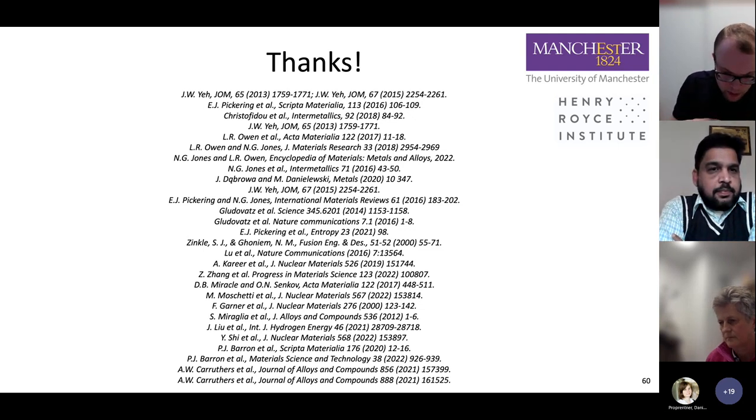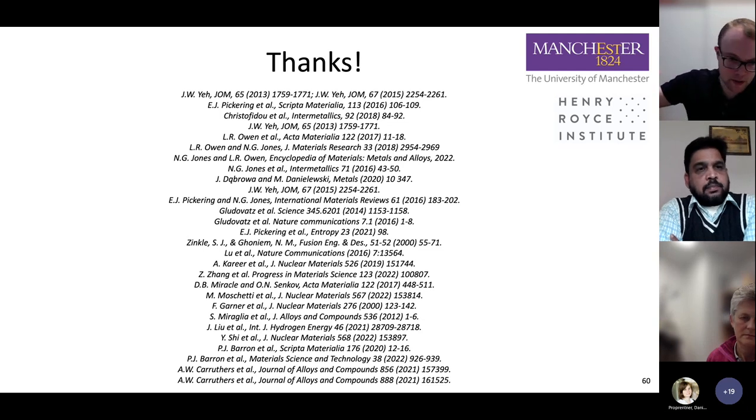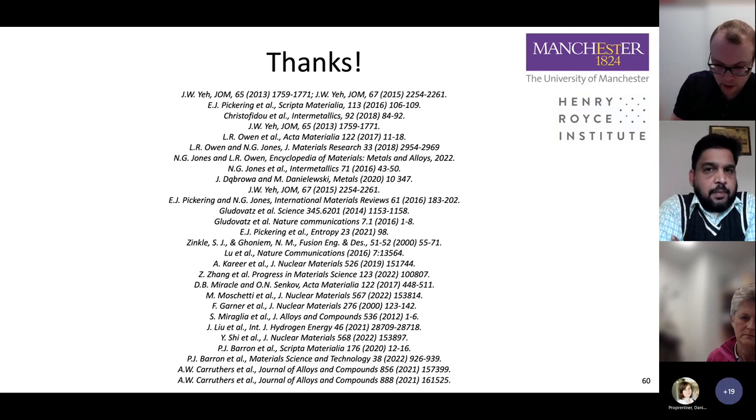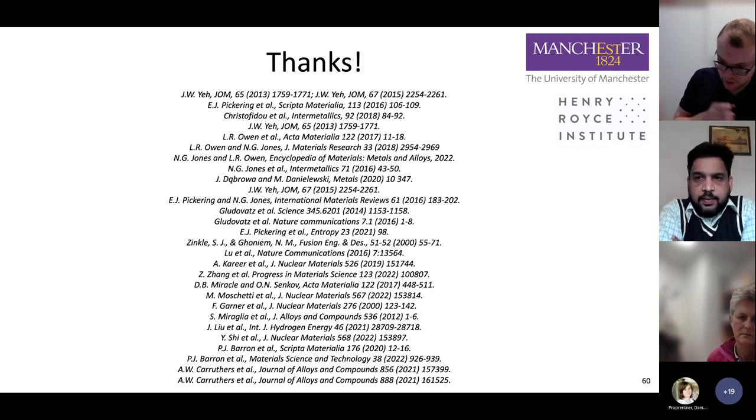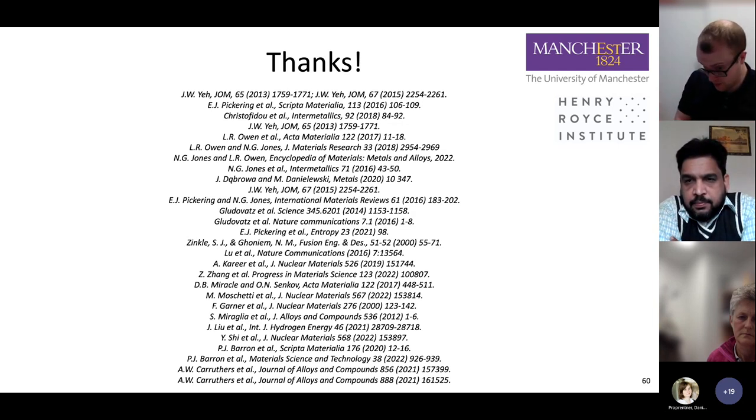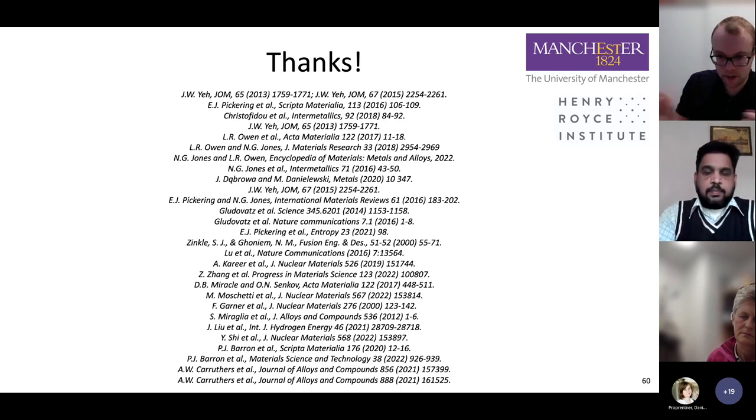And the second thing, there is a lot of work that's been done on the mechanical properties of high-entropy alloys, and I showed some graphs at the start of those exceptional cryogenic properties from FCC high-entropy alloys. A lot of that work, based on altering stacking fault energy and introducing martensitic transformations or twinning, has been led by Dirk Raabe in Germany. That does have direct read across into some, again only some, concentrated steels, like the TWIP type steels, where they're quite highly alloyed, that we are messing around with, for want of a better phrase, in that space.